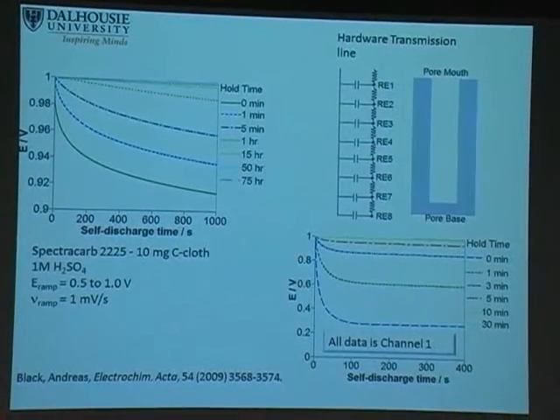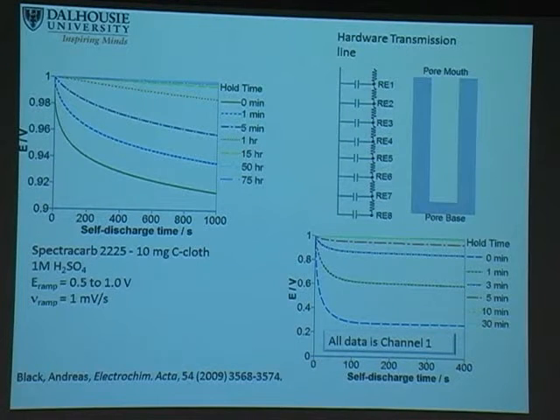And then we did a number of other experiments. One of the ones that we did was to simply add a hold time to the experiment. This is the data from our model pore. As we add a hold time, as we expect, the charge redistribution disappears. When we do the same thing for the carbon electrode, we add a hold time, and again, our self-discharge, or the apparent self-discharge, is decreasing. And again, that suggests that there is a charge redistribution process occurring.